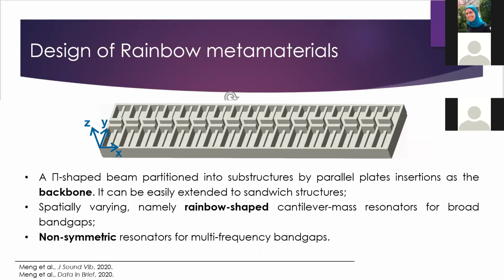So this is our designed rainbow material beam, and this is a Π-shaped beam. A parallel plate partitions the beams into different units. We investigated this host structure because it can be easily extended to sandwich structures, which are very widely used in many engineering areas. This is the backbone, and we attached cantilever mass resonators to the backbone structure, like this. There are two columns of these resonators, and the mass of the resonators can vary along the beam. So we can have spatially varying rainbow-shaped resonators.